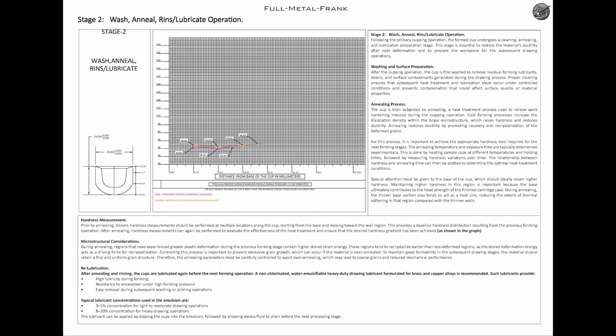Stage 2. Wash, anneal, rinse/lubricate operation. Following the primary cupping operation, the formed cup undergoes a cleaning, annealing, and lubrication preparation stage. This stage is essential to restore the material's ductility after cold deformation and to prepare the workpiece for the subsequent drawing operations. Washing and surface preparation. After the cupping operation, the cup is first washed to remove residual forming lubricants, debris, and surface contaminants generated during the drawing process. Proper cleaning ensures that subsequent heat treatment and lubrication steps occur under controlled conditions and prevents contamination that could affect surface quality or material properties.